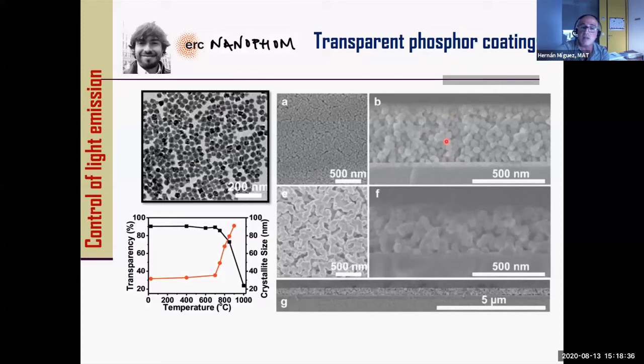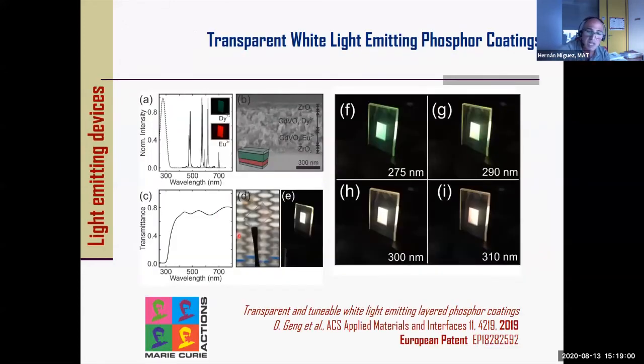You can make a thin film and start heating it, because you need that to get a very good emission. And you see that even at very high temperatures, you still get a very good transparency. This is because you start with very small pieces, and you start bonding and sintering them together, just like you see here. So the result is that you can get completely transparent coatings, but when you excite them, you get this white light emission. This would allow you, for instance, to get a display that is transparent, and when you excite it, you get the white emission that you want.